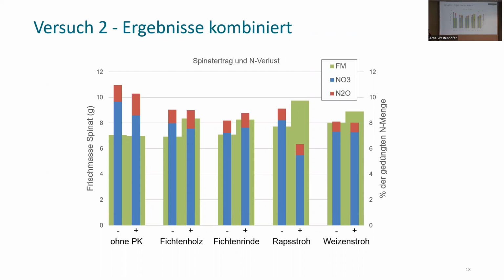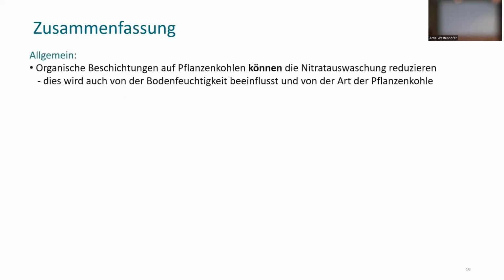In a nutshell, in green in the back, you see the spinach yield. In blue in the front, you see the nitrate leaching effect, a nitrogen loss. And in red, you see the laughing gas emissions and the nitrogen that goes out that way. Here you see the variation without the biochar. 10% is lost through nitrate and laughing gas emissions. What you can see is that our rape straw candidate with coating has the highest spinach yield as compared to the lowest nitrogen losses. Here you see the result.